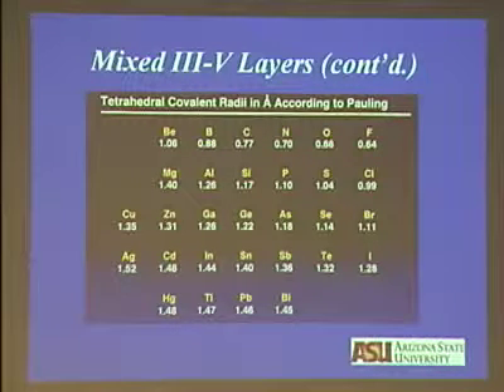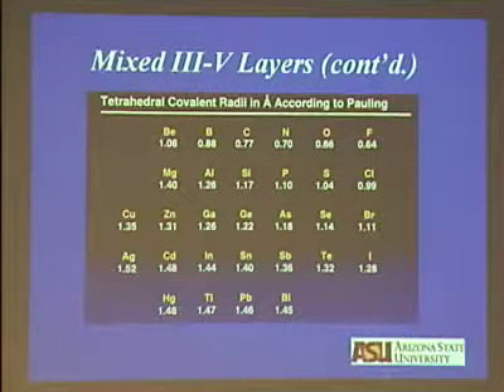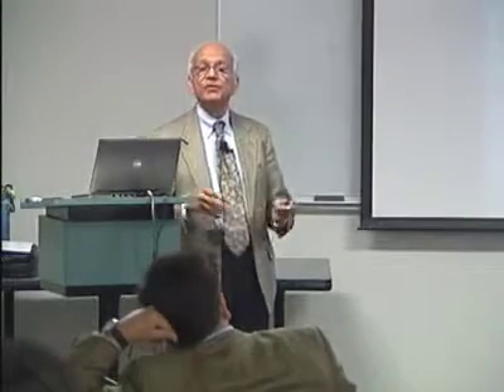Materials, these atoms are tetrahedrally coordinated in the zinc blende structure. Each group 5 atom is connected to 4 group 3 atoms. And the bond length depends on the tetrahedral radius of the material. So indium to group 5 and gallium to group 5 bond lengths are different in the tetrahedra. As a result, there is a tremendous strain in the material. So what the material does is phase separate. You can use a thermodynamic argument, but we use this argument to explain why phase separation occurs.